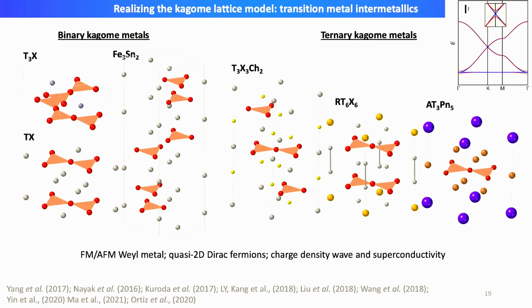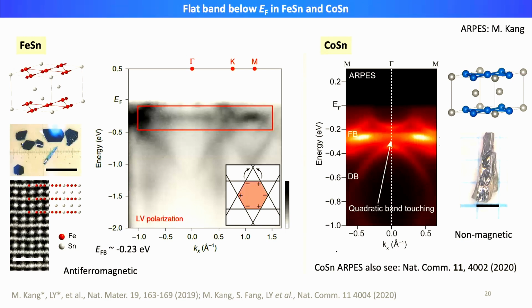Okay, so now we can start to take a look at our experimental results. First of all, I want to show you the photoemission spectroscopy on two isostructural compounds, iron tin and cobalt tin. So if you're not familiar with photoemission spectroscopy, you can just think about it as the experimental measurement of the band dispersion below the Fermi level, right?